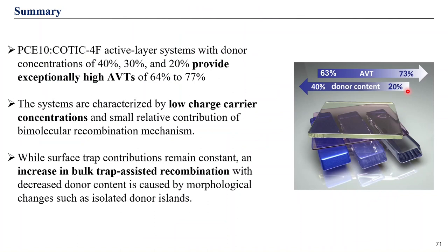So summarizing, I would like to highlight that for system PCE10:COTIC-4F, we managed to achieve record high average visible transmittance of up to 77% by systematic dilution of donor content from 40 to 20%. Due to low charge carrier concentrations in these devices, the relative contribution of bimolecular recombination is quite low, and the dominant recombination mechanisms are trap-assisted recombination via bulk traps and surface traps. And we have shown that surface trap concentration doesn't change with dilution of donor, but bulk trap concentration increases significantly due to formation of morphological traps in the bulk heterojunction layer.